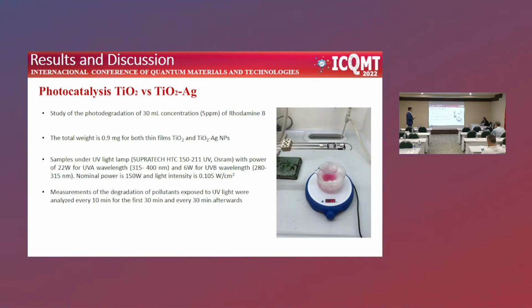Well, how can I do the photocatalysis analysis? Well, we prepare 30 milliliters of Rhodamine B. As you know, Rhodamine B is a common pollutant. The color is rather powerful, a strong pink. So we prepare 5 ppm, and the total weight of the catalyst is 0.9 milligrams.